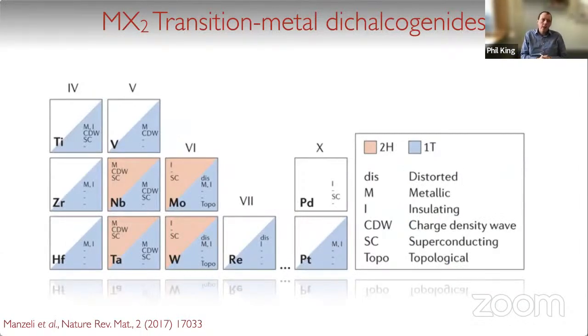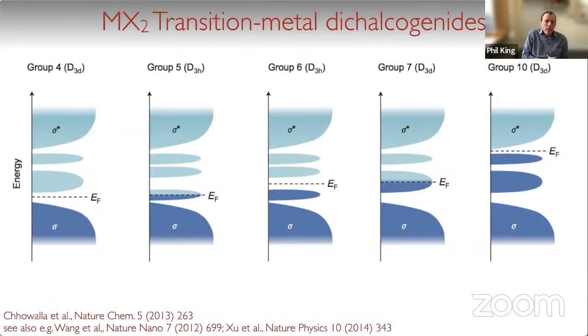And I think one of the nice things in this material family is the huge variety of different properties that we find by changing the transition metal and by changing the chalcogen. And so they host very well-known superconducting systems and charge density wave materials. More recently, there's been a lot of interest in the strong spin orbit semiconductors in the family as well. And it's really generally considered that the main distinction between the different members of this family is really driven by the filling of the transition metal d states. So as you start from the group 4 systems over here, where you have the d states nominally unoccupied, and you start to populate these d states as you move across the series. But what I'd like to really focus on for the first part of the talk today is not the d states themselves, but rather the p states that are derived from the chalcogen in the system.